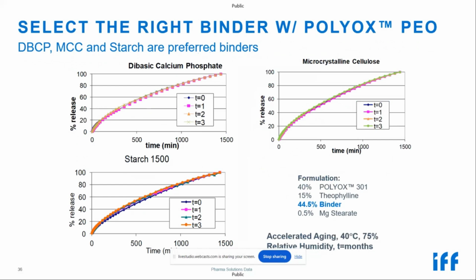There are plenty of binders, though, where we don't see this happening. Dibasic calcium phosphate is one, microcrystalline cellulose, starch 1500. These are all great binders to use with polyethylene oxide in a formulation where we're seeing very good stability in the formulation.